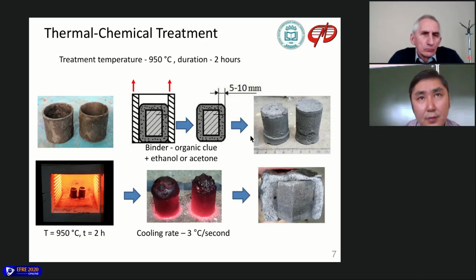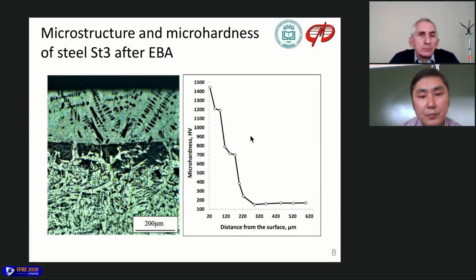and after that, samples were subjected to further preparation procedures such as cross-sectioning. As a result of treatment, we obtained coatings of around 250 micrometers. You can see that dark dendrites are visible, which are placed in light matrix.